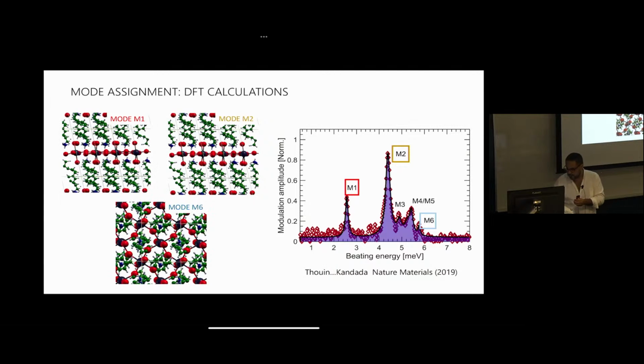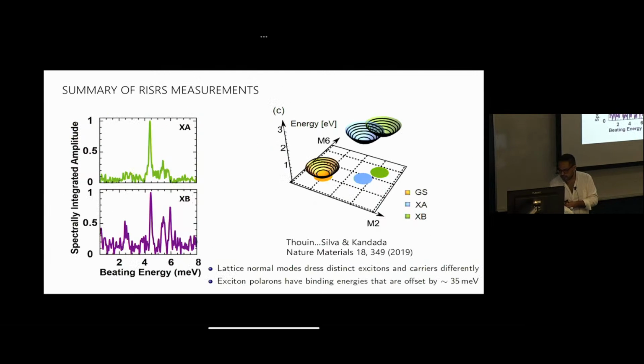So now let's do that by pumping the different modes. And so now we go resonantly with XA. We still have this, what we called M2, that is dominant, but you notice that some of the amplitude of the lower frequency phonons is much lower. Okay, so this mode is still very centrally responsible for dressing the exciton, dressing coupling to XA and modulating that. And so that's still the case. But these much less so than for the photocarriers.